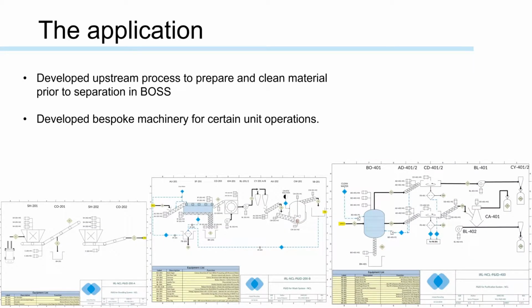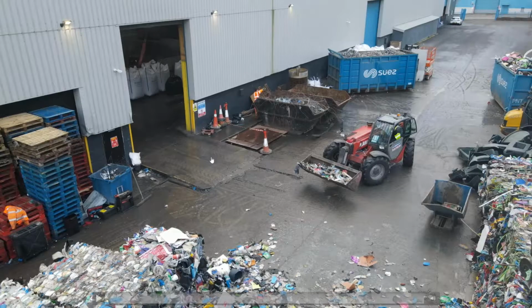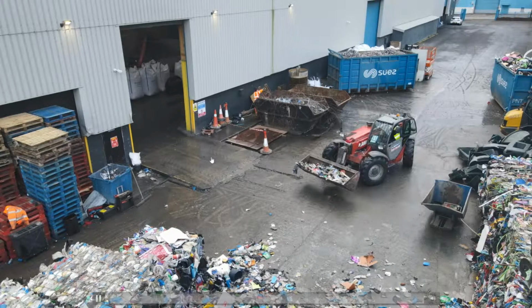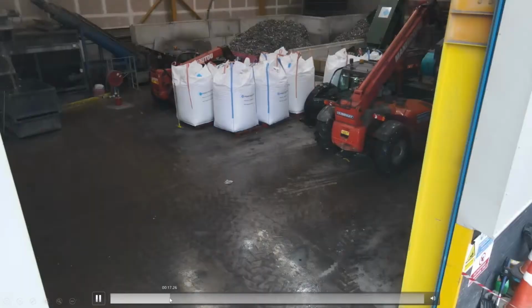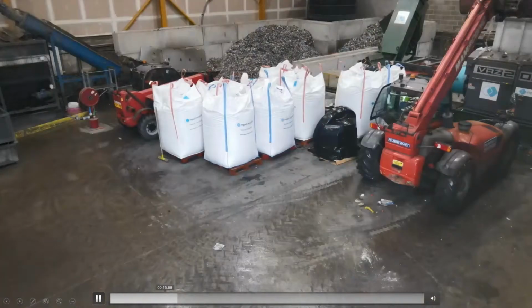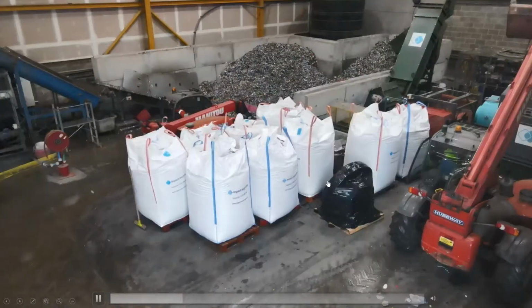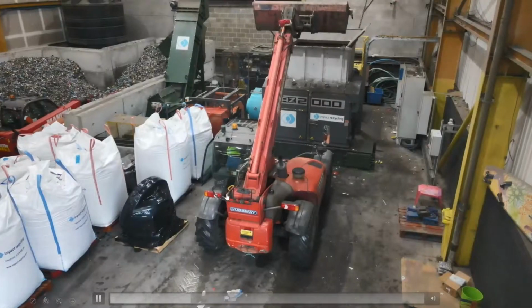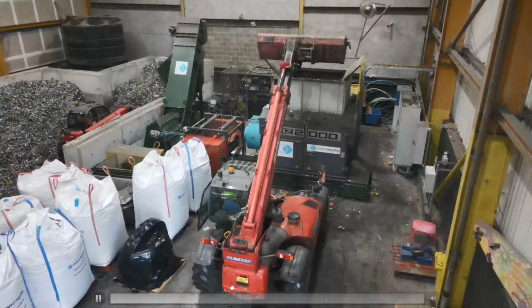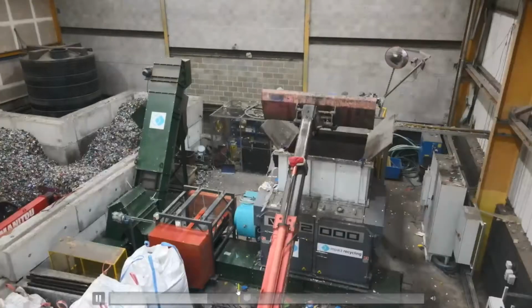But to do this, we did need to develop some upstream IP. So we developed a unique shred wash pre-purification system to feed our proprietary patented BOSS system. Our material comes in as you would put it in your bin. We shred it down to 50 millimeters and remove the metal. We put that into intermediate storage because the shredder is obviously a very lumpy output.